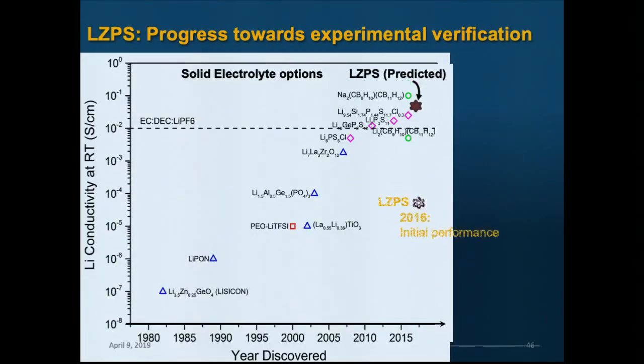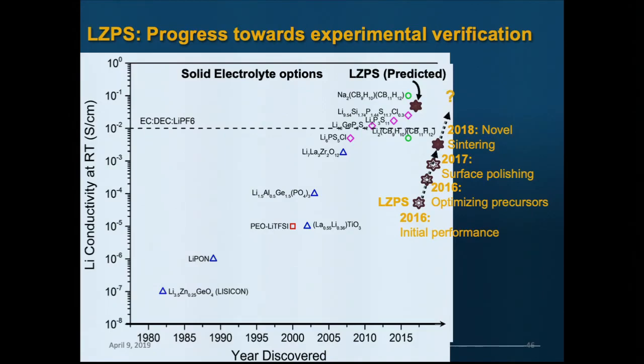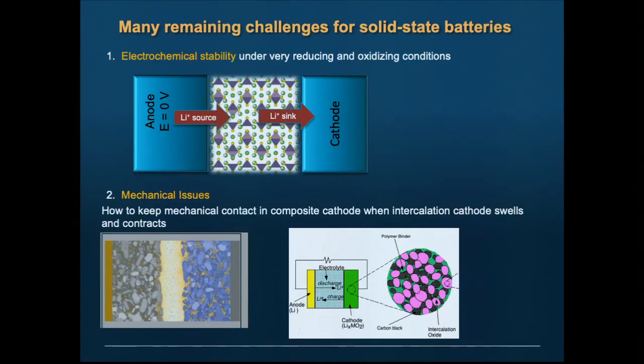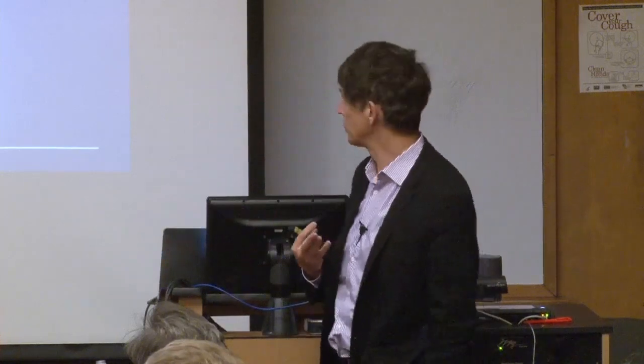We have been able to get reasonably close over many years by working with our collaborators at Samsung, by improving processing methods. And we are essentially now within an order of magnitude of the target. That may seem terrible, but in the world of ionic conductors, an order of magnitude is not a lot in terms of milli electron volts. So by now, it is among the best conductors, but it is not nearly as good yet as we predicted. OK. So I think we start to know fairly well how to make good conductors. And I think what we're learning is that there are probably many more good conductors for ions than we actually thought there were, that this is actually not as unusual as we thought.